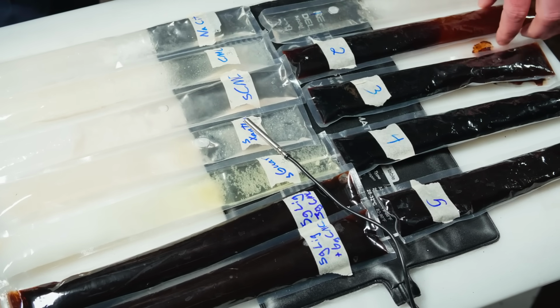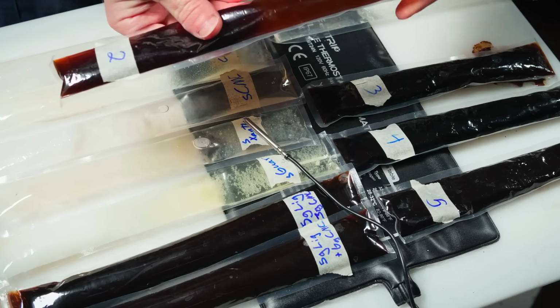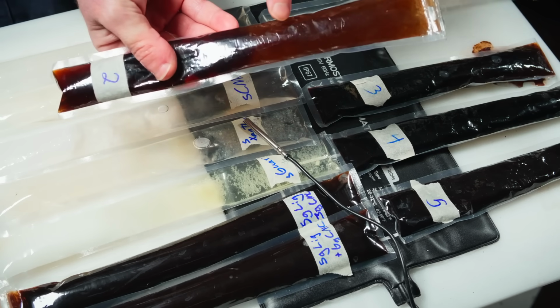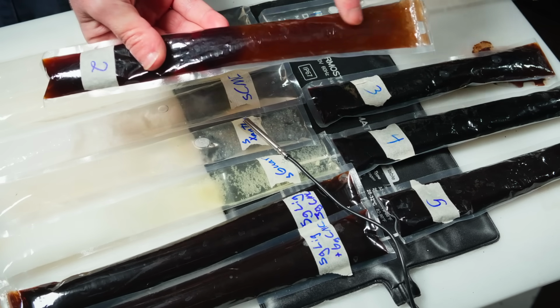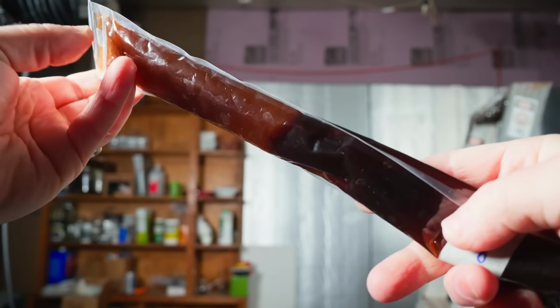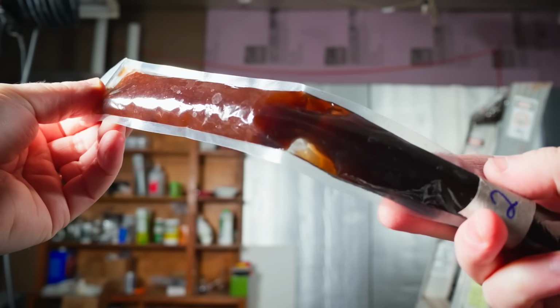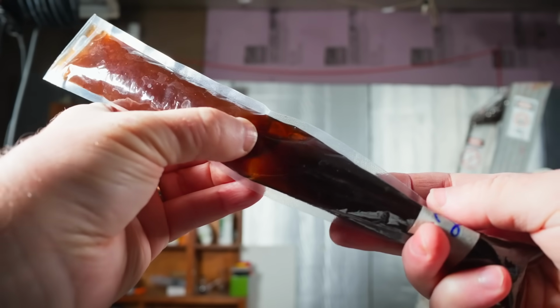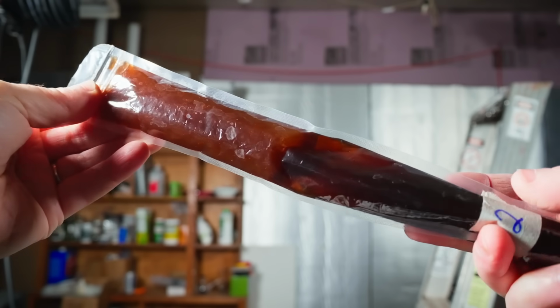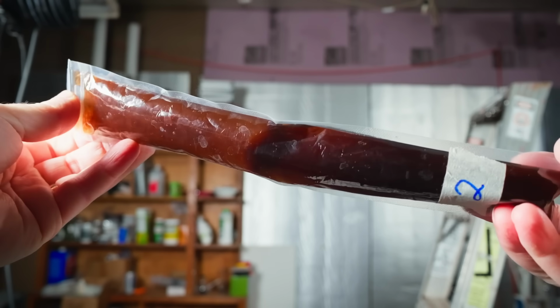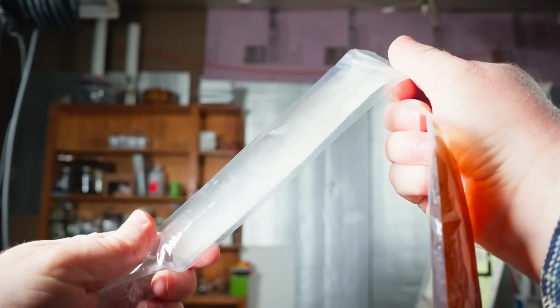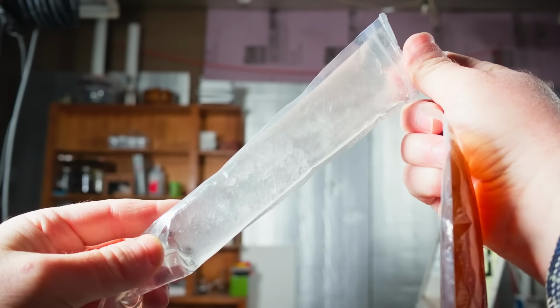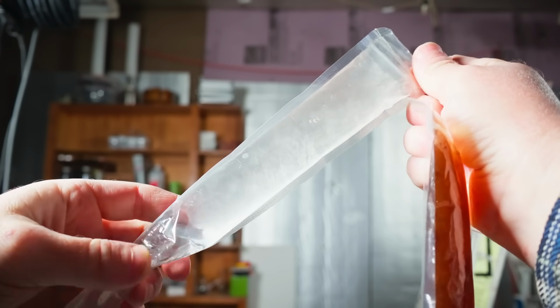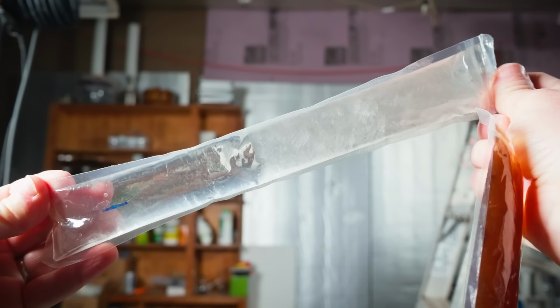Number 2, however, seems to have frozen in a fairly homogeneous structure toward the cold end of the sample. This is looking pretty good, pretty much how it did in the vertical cool down test. And I think that it is looking better than the control. The control has fairly large crystal structures. It's very hard at that boundary layer. That's to be expected with the control.